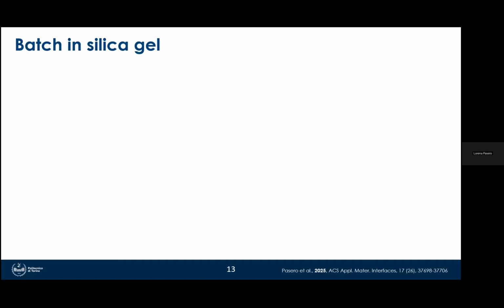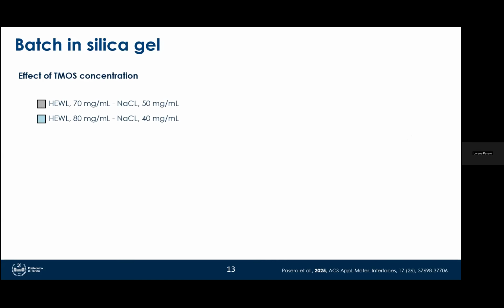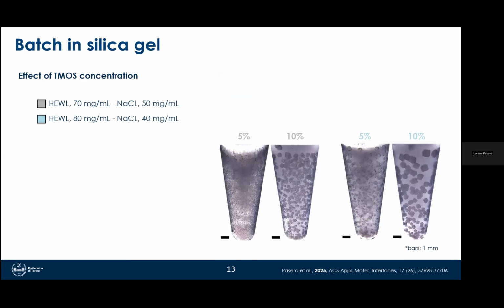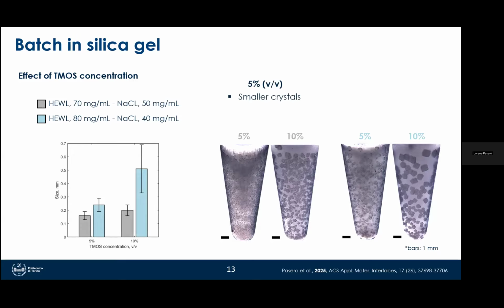Here we compared the nucleation effect of 5 and 10% of TMOS for 2 different combinations of protein and salt, which were chosen to achieve overall a similar supersaturation inside the gel. So we compared the crystallization pattern at 5 and 10% TMOS for the two different conditions. And we saw that at 5% TMOS, we obtained overall smaller crystals, and the gel appeared to be more viscous, since the gelation was not so complete.